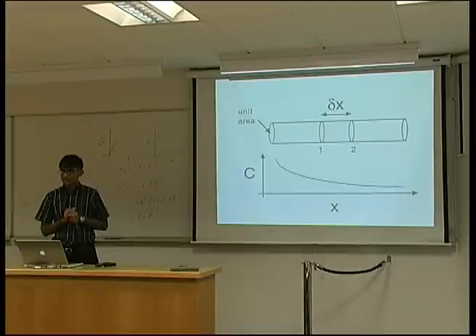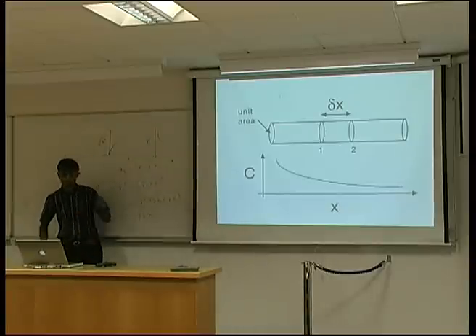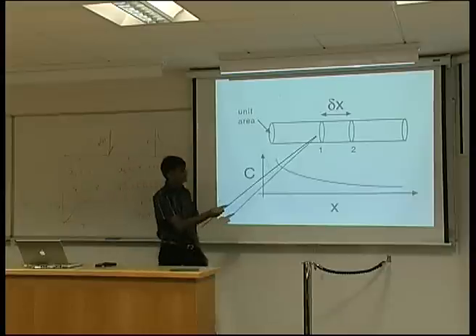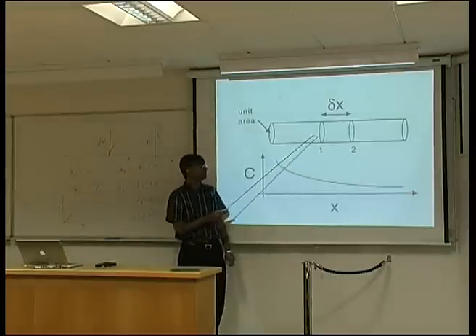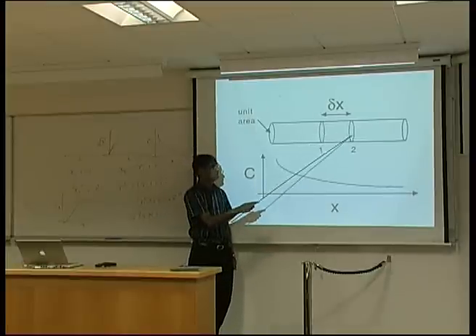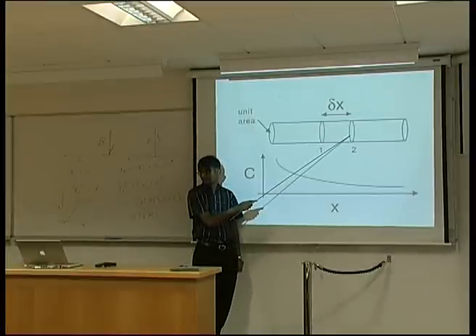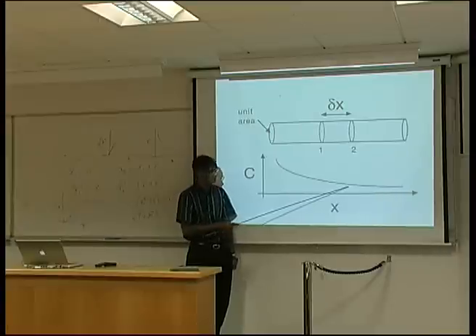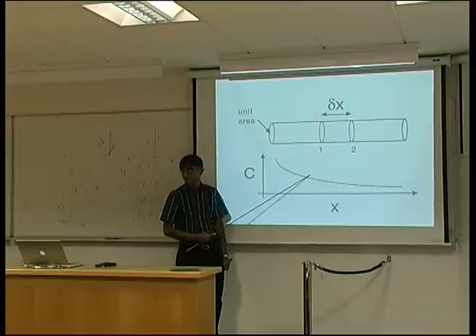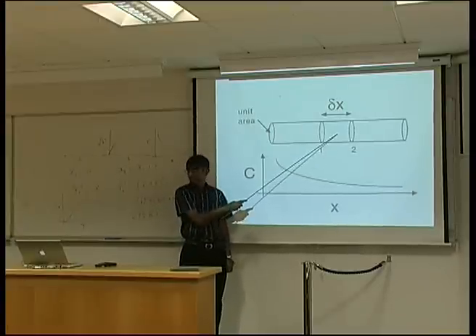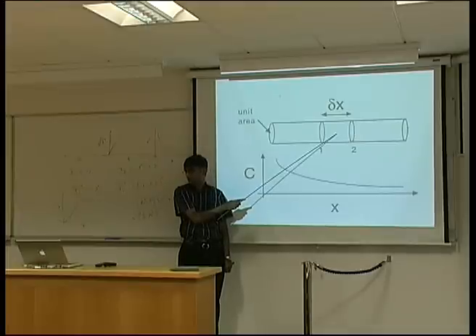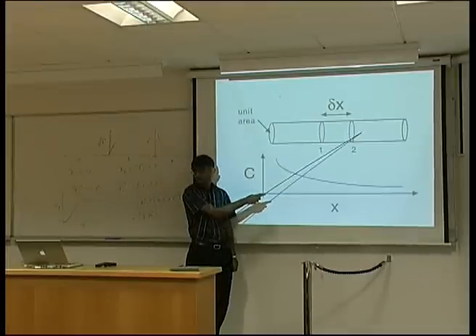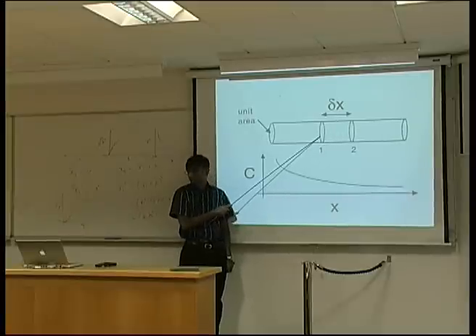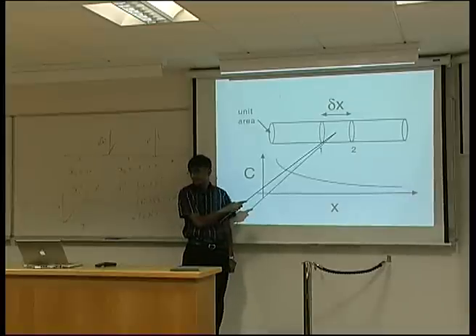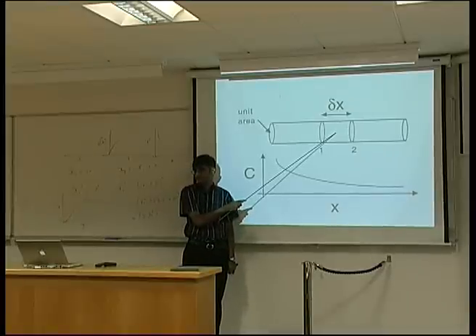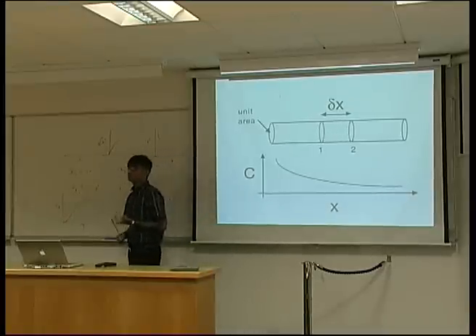Okay, let's now consider the case where we don't have a constant concentration gradient. So obviously, if I consider two planes here, the flux into this plane will be different from the flux into this plane, right? Because the gradient here is shallower than the gradient here. That means that there will be a buildup of solute in this region. If the flux leaving this space is less than the flux entering it, then clearly the concentration here will change, right? So now we have a time dependence of flux.